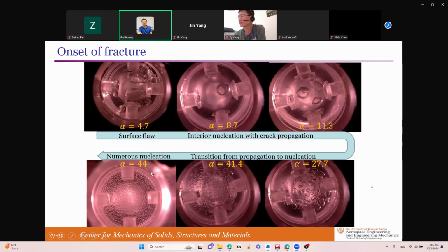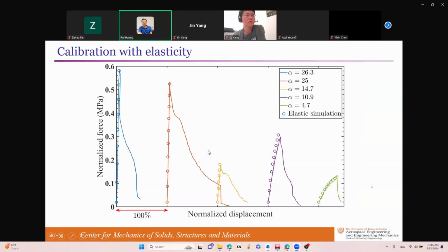In a very thin adhesive layer, you would see very nice nucleation over the entire cross section. So if you look at the specimen at this point, it looks like a honeycomb. It's got all these multiple cracks. The gap between the cracks is filled with highly elongated material that then severs by other mechanisms much later. All right. So that's the experimental observation. Now we need to figure out, there are some kinematic quantities that we can extract from this, but we also need to figure out what criteria for nucleation of cavities we can develop from it.